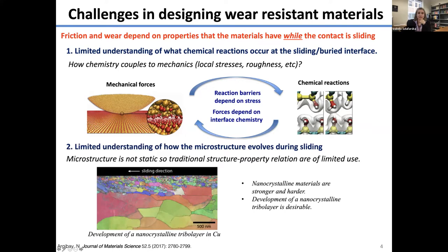The second aspect is microstructural evolution. The microstructure that develops in sliding contacts near a sliding interface, the so-called tribolayer, can be very different from the original material and from the microstructure that exists far away from the interface. So the traditional structure-property relations that we learn about in courses or that have been discovered are of limited use because of the dynamic nature of the contact.